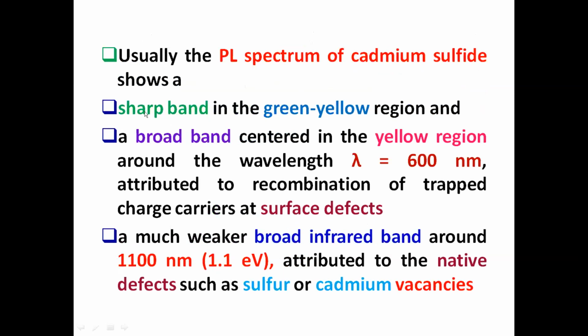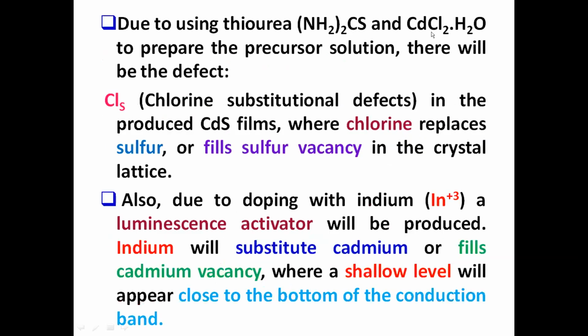They represent bands. One of them the sharp band in the green-yellow region, then a broad band in the yellow region centered at about 600 nanometer, and it is attributed to surface defects. Then a weaker band in the infrared region centered at about 1100 nanometer, and it is due to native defects such as sulfur vacancies and cadmium vacancies. Due to using thiourea and cadmium chloride, there will be another defect. It is known as ClS, which means chlorine replaces sulfur in the crystal lattice.